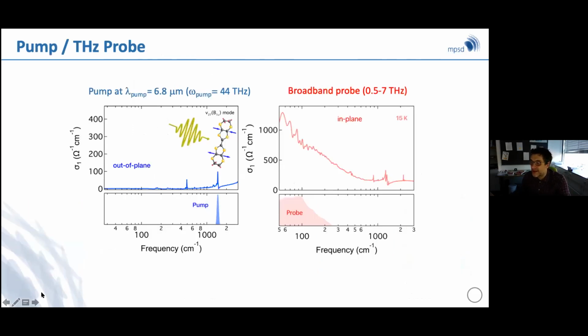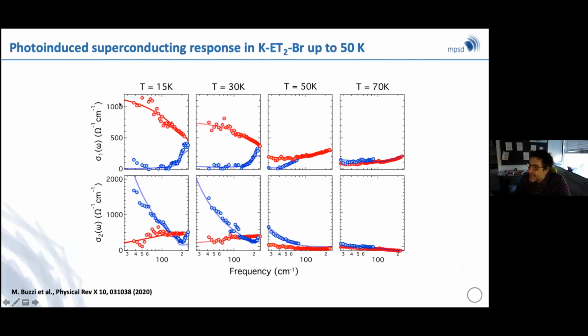And so what Michele did was to take these compounds and excite them in ways similar to what I was doing with the buckyballs. And lo and behold, what he discovered was an even clearer demonstration, in terms of quantitative details and sum rule transfer, of a transformation between a metallic set of properties at various temperatures and a light-induced superconducting state, in which basically all the spectral weight from the metal is being transferred to a pole at zero frequency, respecting a non-equilibrium version of the sum rules.